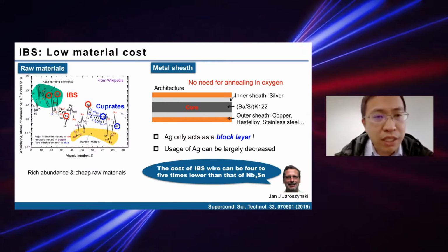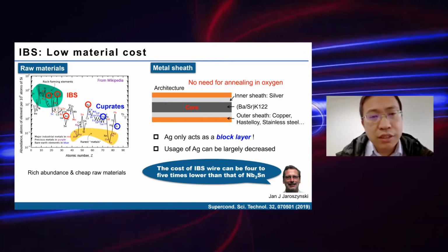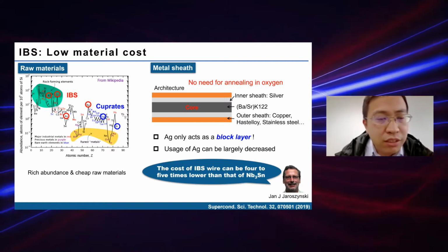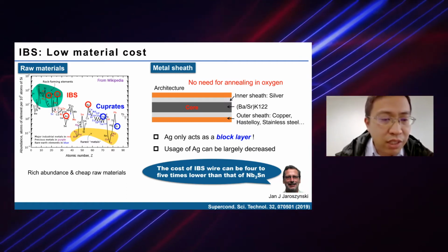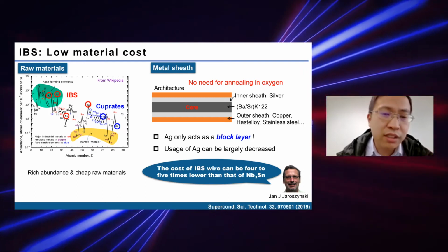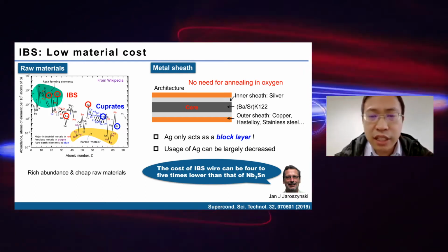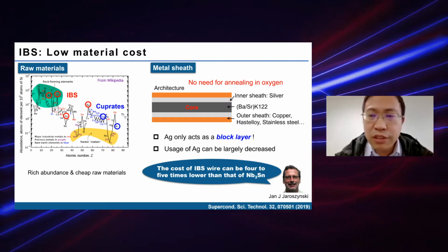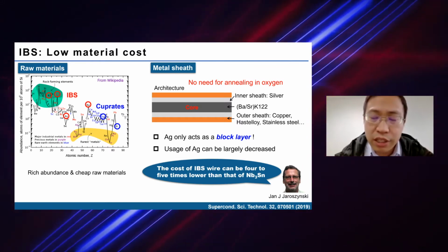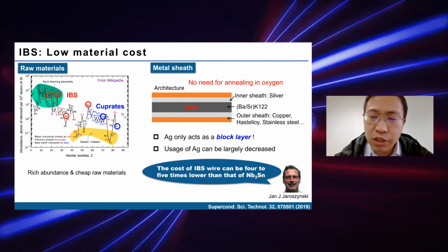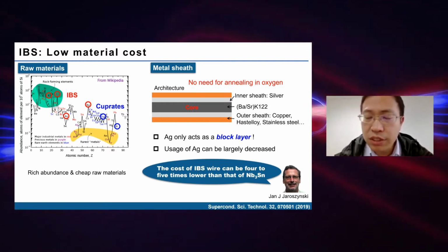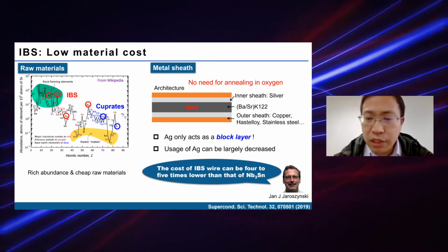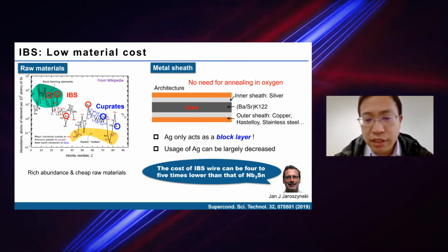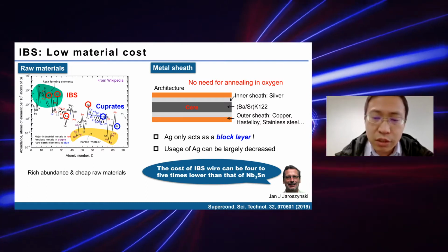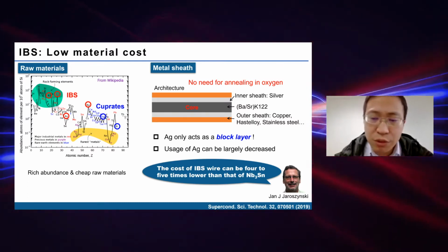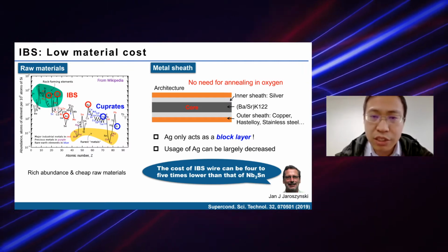Another advantage of IBS is their low material cost. On the one hand, iron-based superconductors include elements that have richer abundance than the cuprates. On the other hand, because there is no need for annealing in oxygen, we can directly combine stronger outer sheaths such as copper alloy on the outside, and silver only acts as a barrier layer. So the cost of IBS wires and tapes can be 4 to 5 times lower than that of niobium 3 tin.